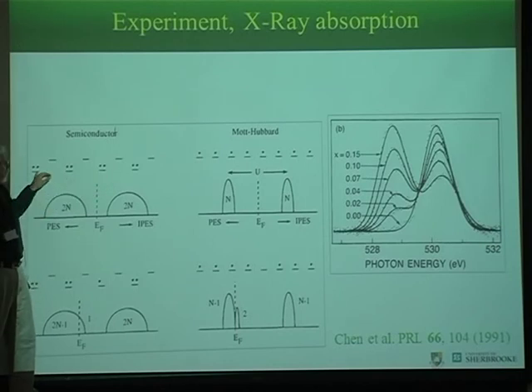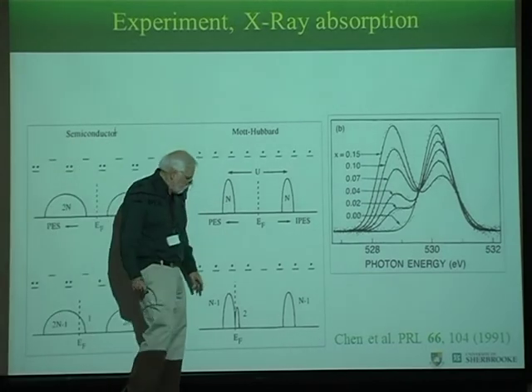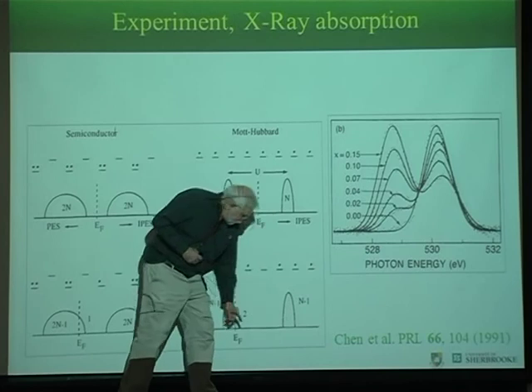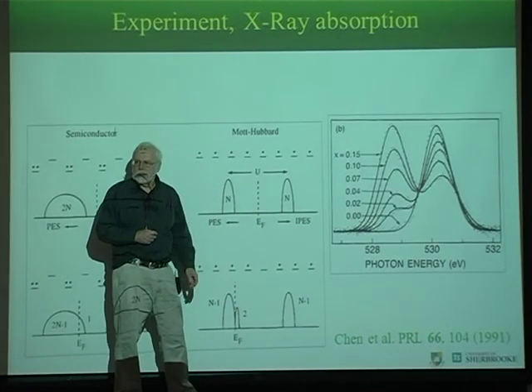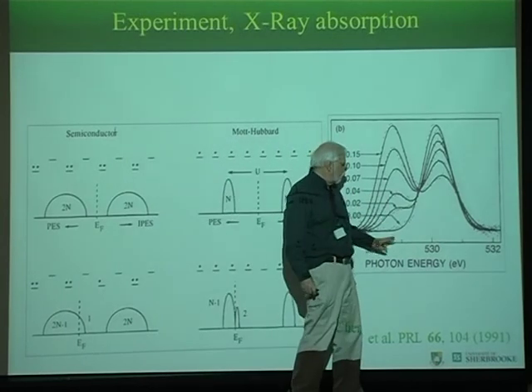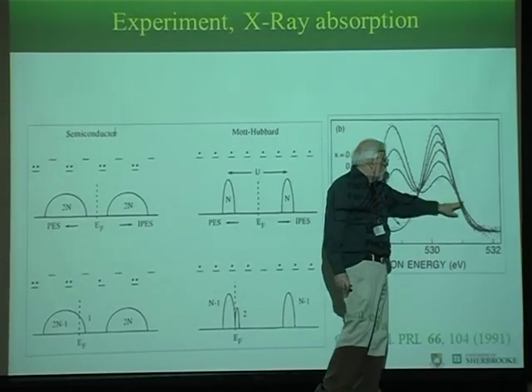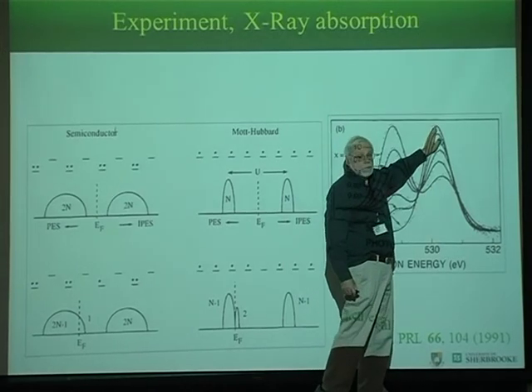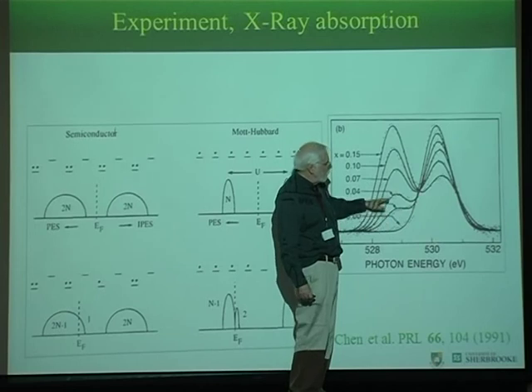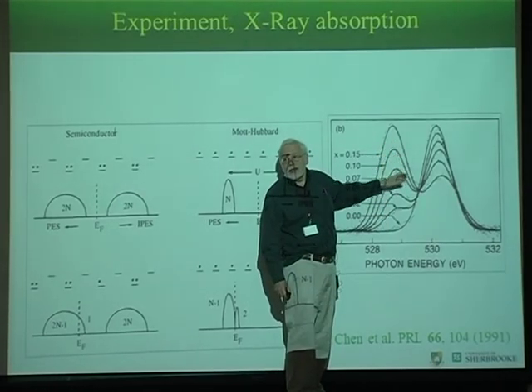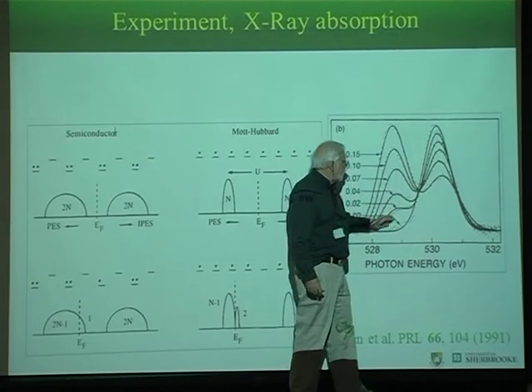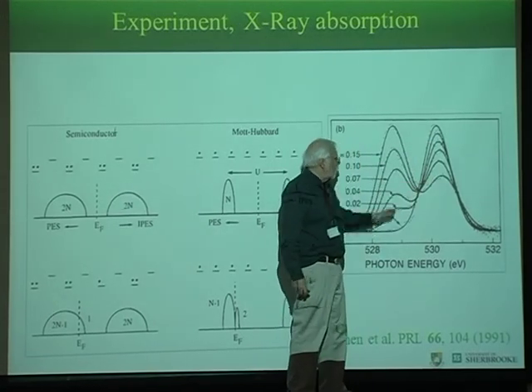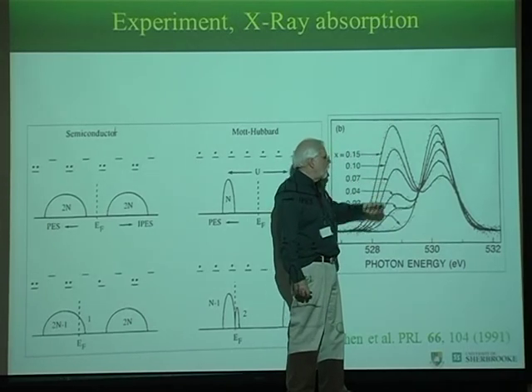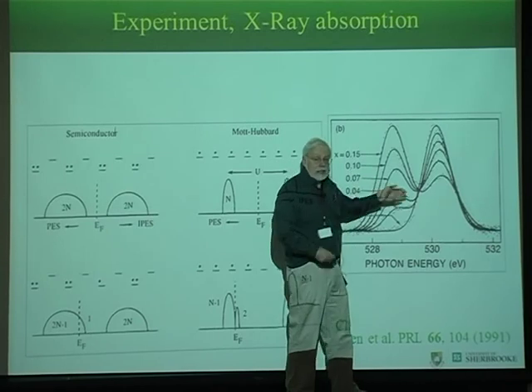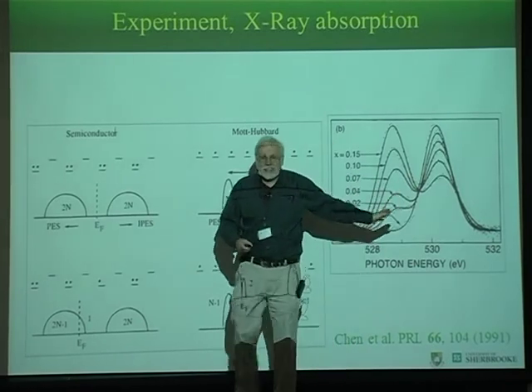Here I just remove one electron to show the effect. In this case, this goes down with doping, and this goes up twice as fast with doping. And this is what we see here in these curves. So at half filling, there's only one bump. And if it was a semiconductor, that bump would stay the same, and there would be another bump here that would grow linearly with the doping. Here instead, this bump is going down linearly with doping, and this one is going up twice as fast. Actually, when I say twice, it's not exactly one or two, but qualitatively it is clear what happens.